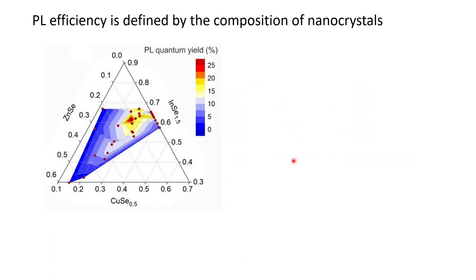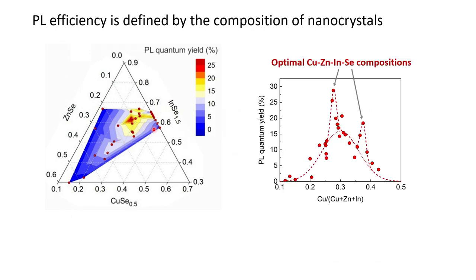So what you see on the slide are the measurements of photoluminescence efficiency, which is, in other words, how efficient is light coming out of the material. So we see this as a function of different compositions. Once again, all these red points here are the compositions which we achieved experimentally. They have the same size, but different composition. And we immediately see, if I plot it for you, for example, on the scale of copper content, that there are two outliers. There are two good outliers because the properties of these two materials, the light they shine back to us, is superior in comparison to their neighbors. So we found some sort of optimal copper, zinc, indium, selenide compositions in terms of lighting applications.